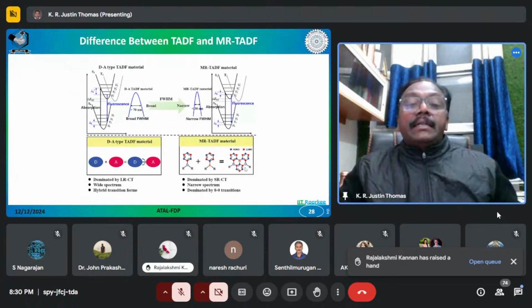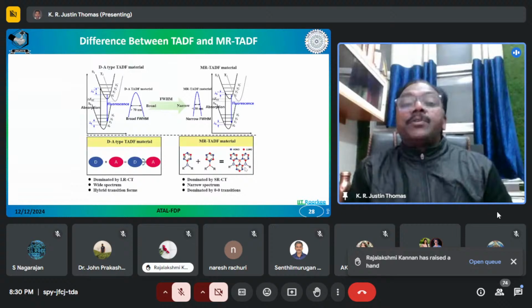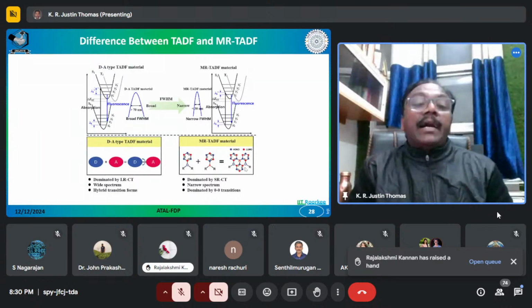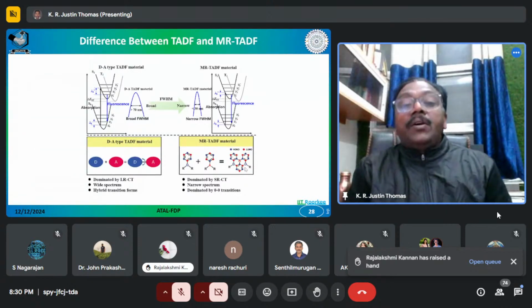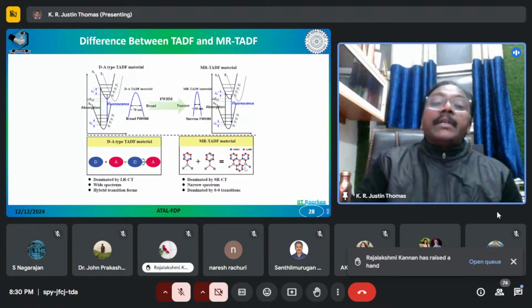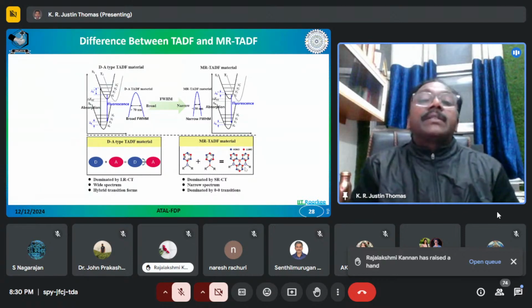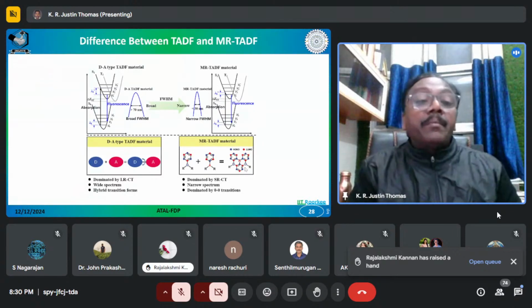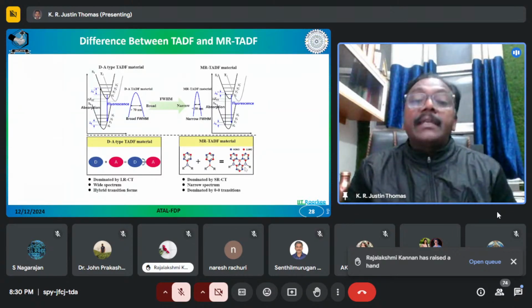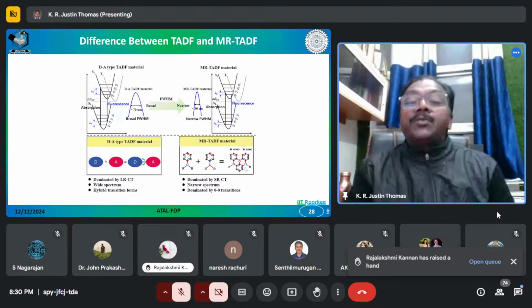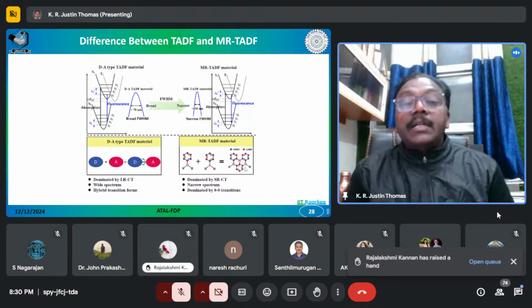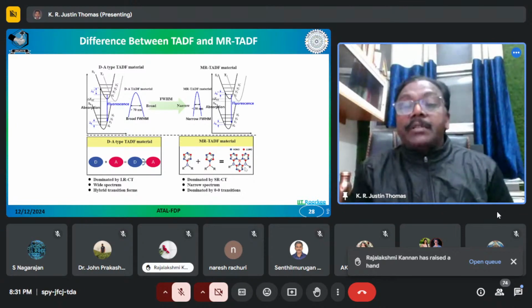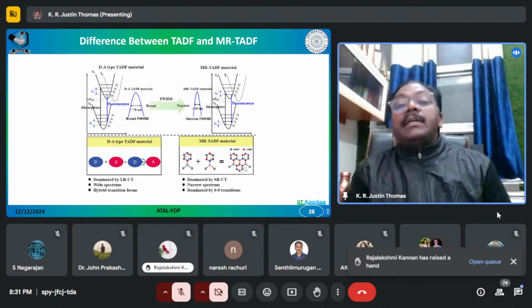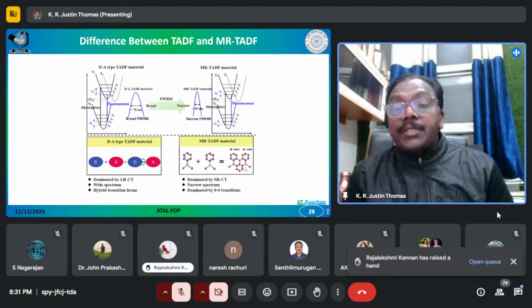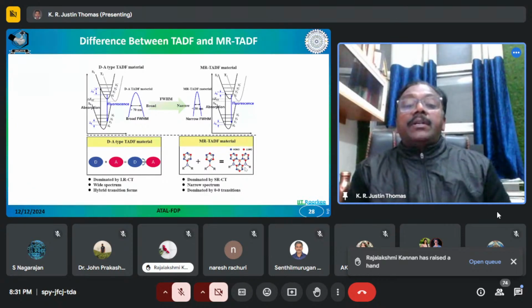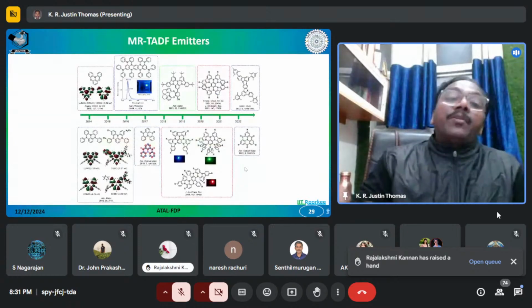And this emission is dominated by 0 to 0 transitions rather than other transition forms. Okay, so this way, these MRTADF materials are more attractive. It is giving a solution for the problem that we have faced with the TADF emitters, that is the broad emission and a weak emission. So now you have a rigid molecule having a short range charge transfer, and that is not leading to any relaxation. So you have a very good narrow emission with high quantum efficiency.